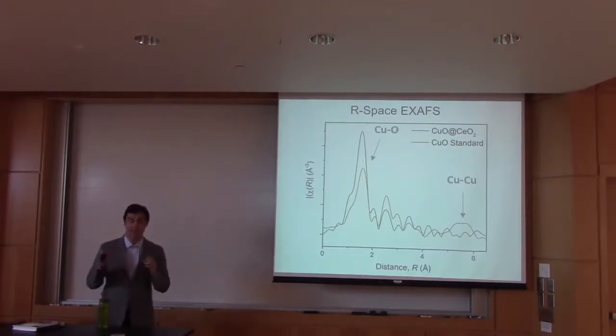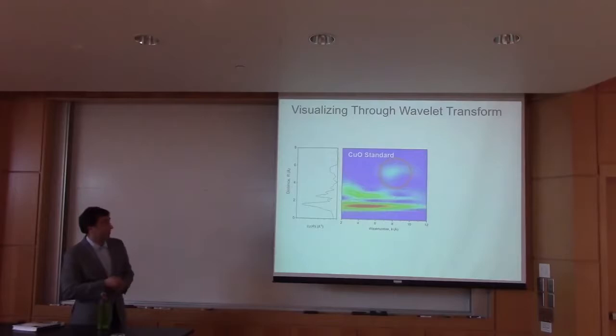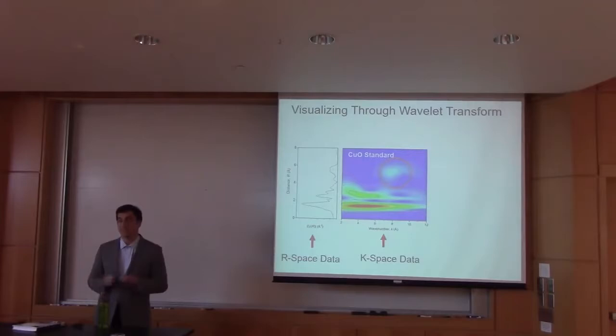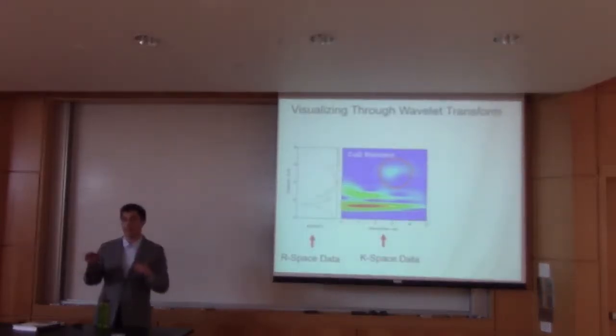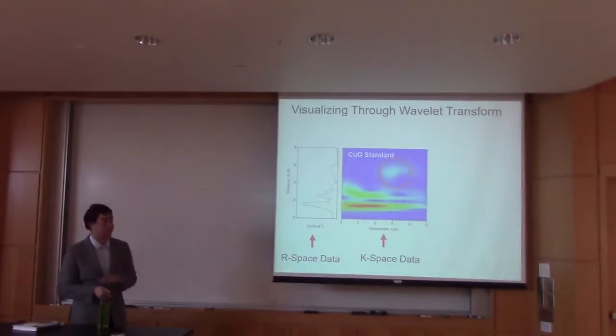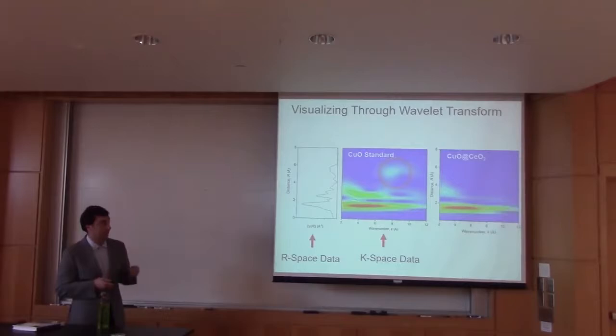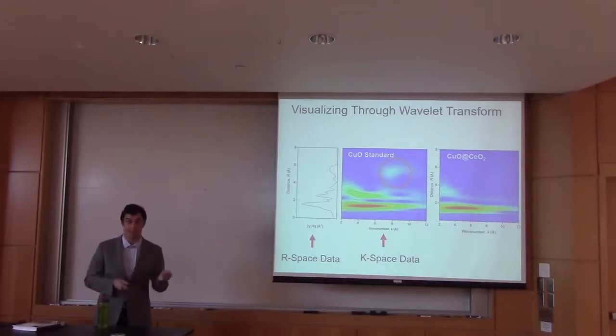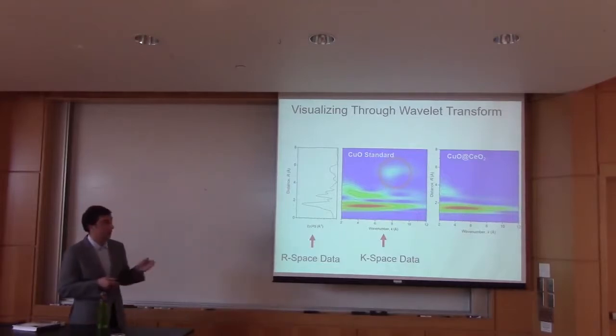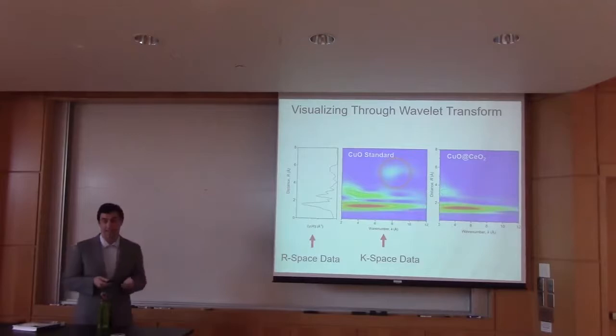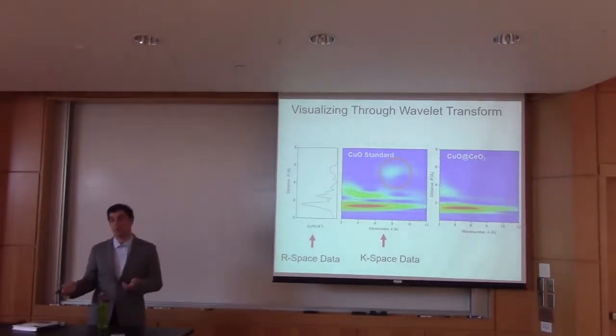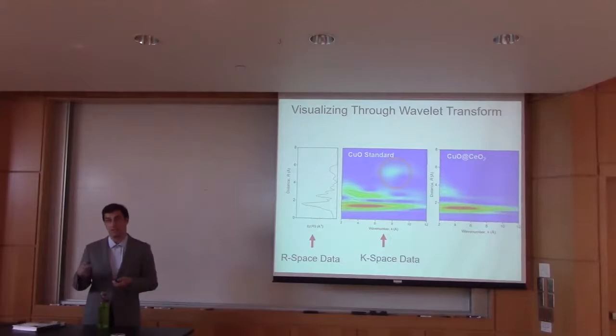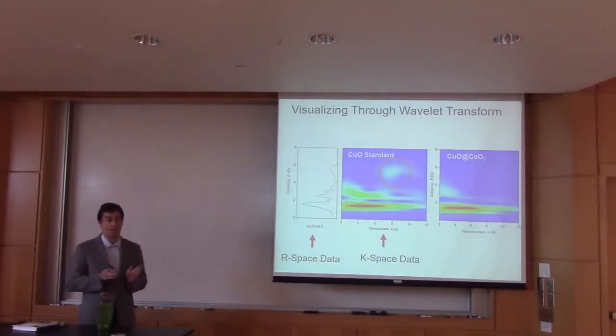And it looks kind of like a heat map or infrared. So here it is. Here is our R-space data, and we're plotting it against the K-space data, but we've taken that K-space data and are now looking top-down on it and creating this topography of peaks as we correlate these two plots. So we're still looking at our copper oxide standard and comparing it to our catalyst, and this big circle indicates those copper-copper scattering peaks and copper-copper scattering distance, which is very apparent in our standard and entirely absent in our catalyst, which again is just another way to show that we have succeeded in what we set out to do, at least to some extent, in minimizing those copper oxide domains.